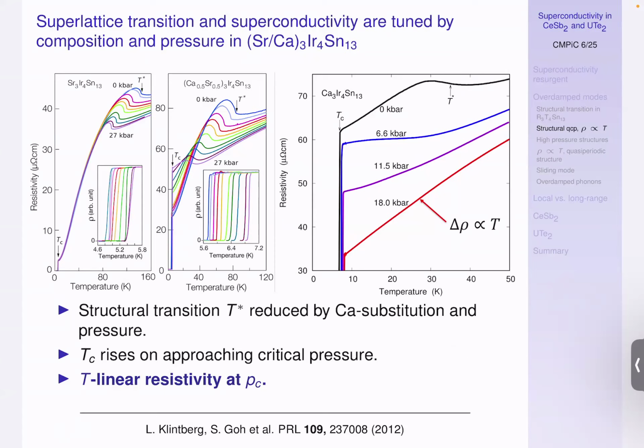It's like 150 Kelvin. We bring it down by pressure, but it doesn't go all the way down. It's not enough. So then we replace some of the strontium by calcium, which is smaller. So now T star starts at 80 Kelvin, and we can bring it down at 27 kilobar to about 30 Kelvin. But it's still not all the way down. And there's actually a lot of other stuff going on which might be interesting, like why does rho zero go up so much? Anyway, then next step, replace all the strontium by calcium.